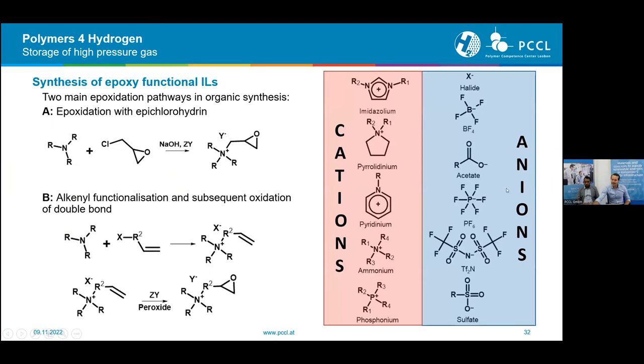Unfortunately, I have to once again do a little excursion into the chemistry for the synthesis of those resins. Usually there are two main pathways to produce epoxy resins, or most used. The first one is with epichlorohydrin. That is also used for the most popular, most common resin, which is the bisphenol A-based resin. So you let it react with this epichlorohydrin, and in this case, it then in the same step epoxidizes it, and you come out with those epoxy groups on the side. Of course, you could also pre-react this with something else to get different side groups.